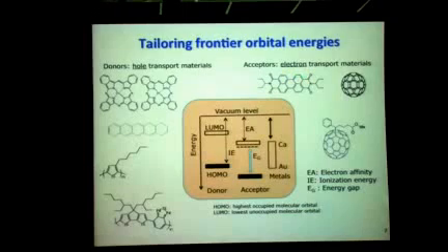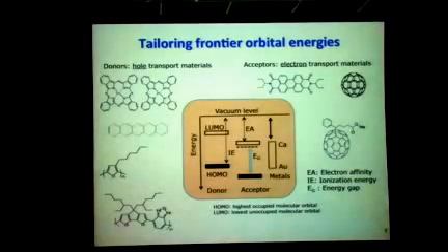On the other hand, through chemical design you can make molecules that are electron deficient, or acceptors, which generally have fairly large electron affinities. You can push the LUMO level sufficiently down away from the vacuum level so that it lines up with low work function metals such as calcium. This is very useful for making solid state devices where you need to efficiently inject or extract holes and electrons.